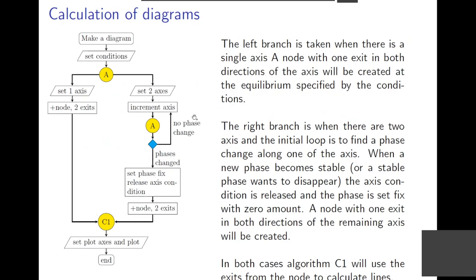So this is the beginning of a calculation of a diagram. You again have to set conditions. You make an equilibrium calculation. If that converged, you can set either one axis for a step calculation or two axes for a phase diagram. And if you want to have two axes, you have to find the zero phase fraction line. So the program will iterate here until it finds a phase change. And then it will follow that phase change. So during the mapping or stepping, it creates node points where two lines meet. And in the initial one, you have only exits. There is no line arriving at this node. But in both cases, you will use the same algorithm to calculate both the property diagram and the phase diagram. And that is algorithm C1.